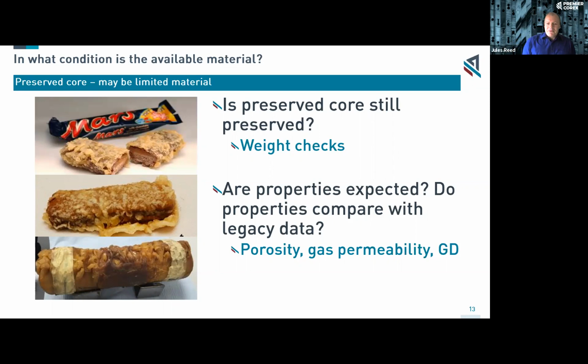We have to ask the question, has the preservation of that core remained intact throughout its storage? And one of the ways that we can do that, we can look at weight checks. So we should weigh the samples before they're placed into wax preservation. We can then weigh the sample after the wax preservation. And if they're the same weight, basically nothing has changed through that process. No fluids have evaporated throughout that storage period. But we need to make those checks.